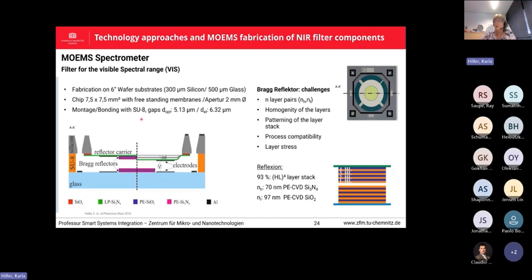Bragg reflector means in principle we have alternating layers with low refractive index like silicon dioxide and higher refractive index like silicon nitride. So here the contrast is not so high. That's why we need a double layer stack of 4 layers to get these 93% reflection. So we also tried titanium oxide instead of silicon nitride, which has a little bit higher contrast. So we could save 1 pair of layer stacks.